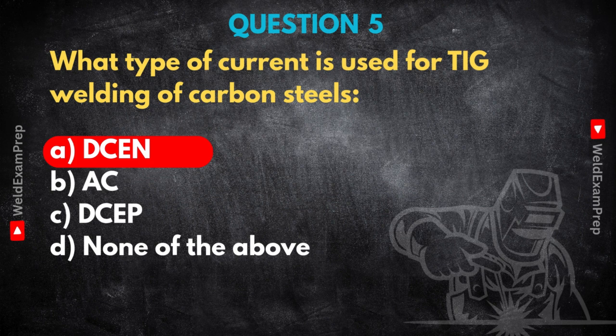Yes, DCEN. This is absolutely fundamental stuff. Every inspector has to know this cold. So DC, direct current, means the electricity flows one way. With DCEN, electrode negative, the tungsten electrode is hooked up to the negative terminal. What this does is focus most of the heat, maybe 2/3 of it, onto the workpiece, the metal you're welding. That's exactly what you want for carbon steel. Good heat input for good penetration, making a strong weld.